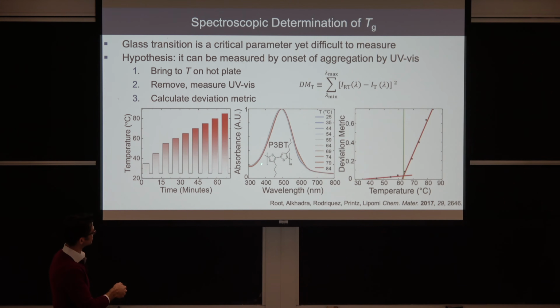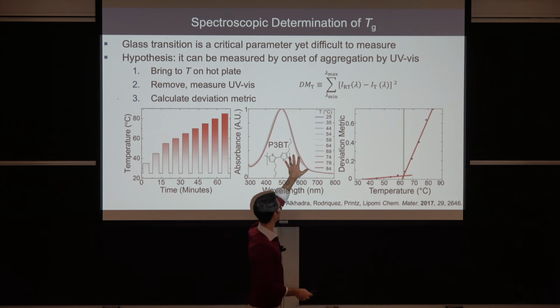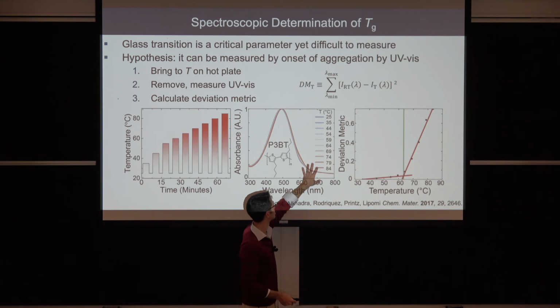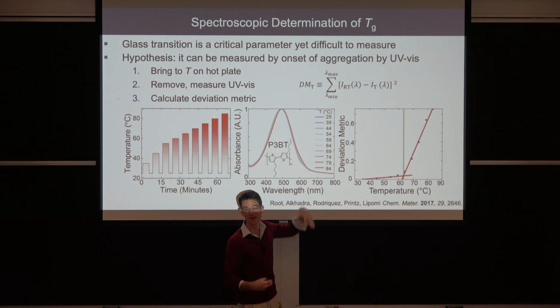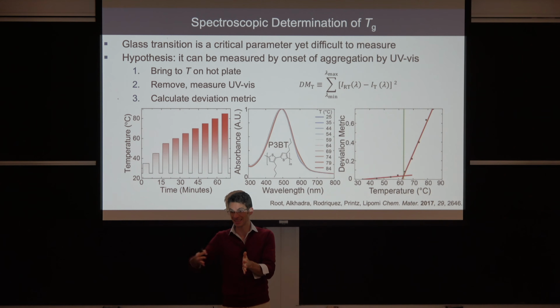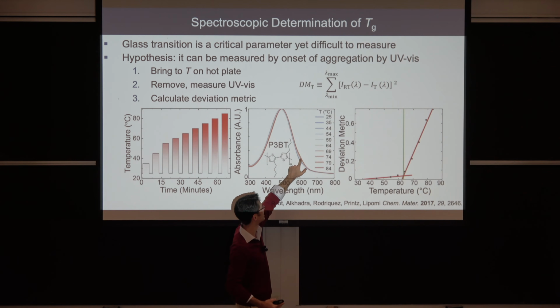Basically, what you do is you measure these UV-vis spectra and you find where the deviation is. And as you integrate all of these spectra and you square the differences, this is where these crystallites absorb. This is where they're aggregates. Before they're crystallites, they're aggregates. These are where these aggregates and then later crystallites absorb, right here.